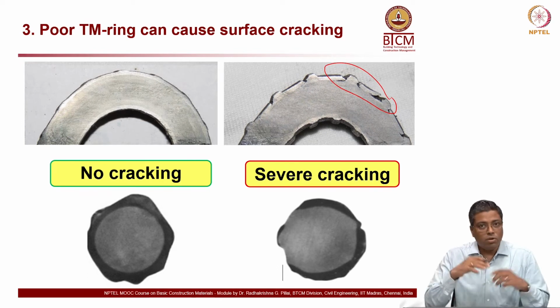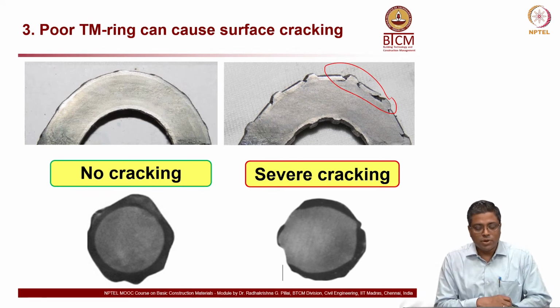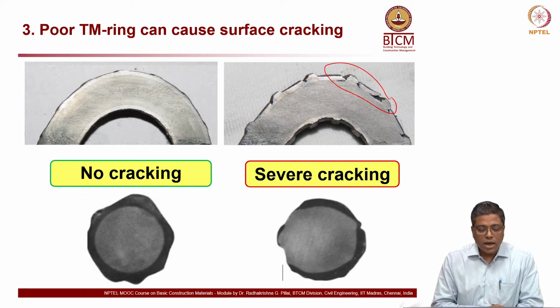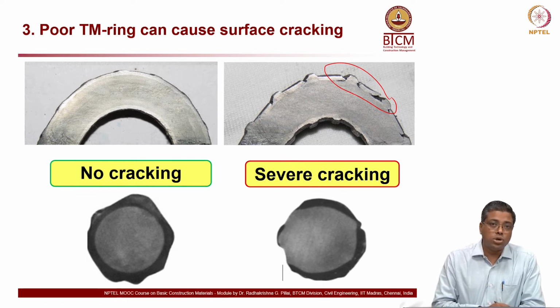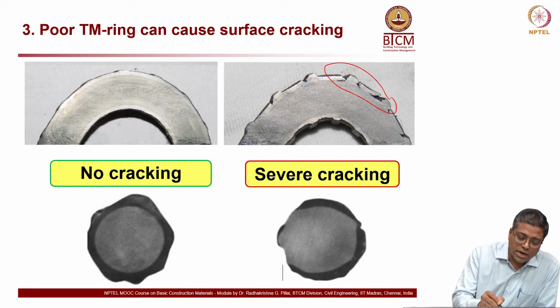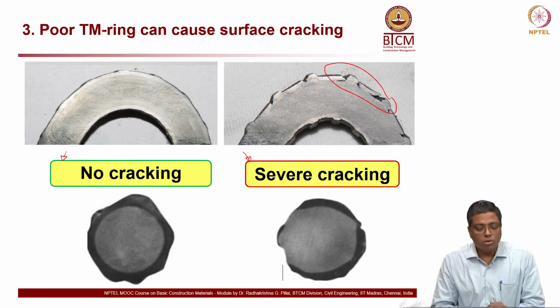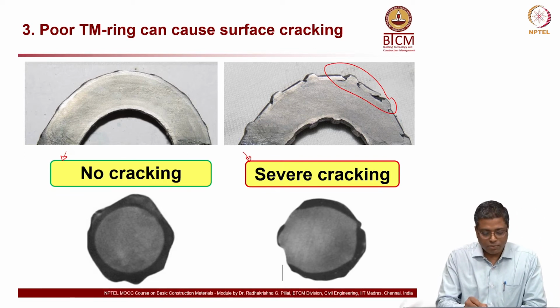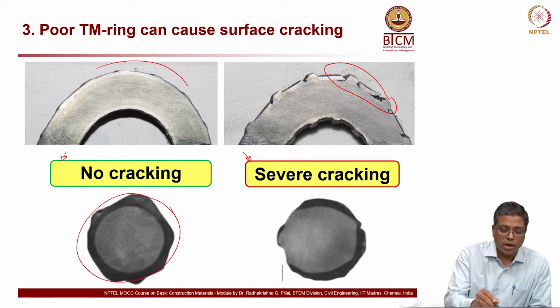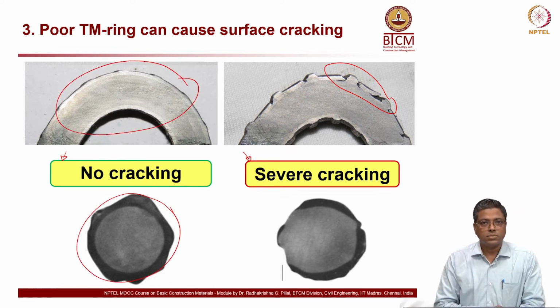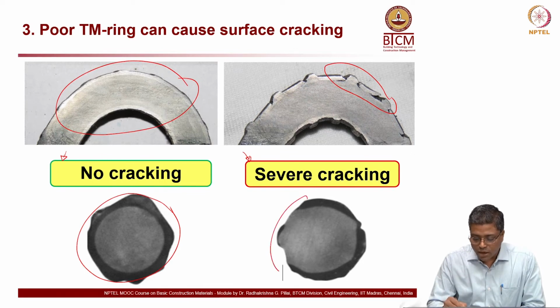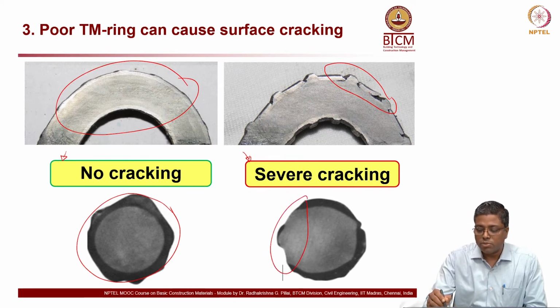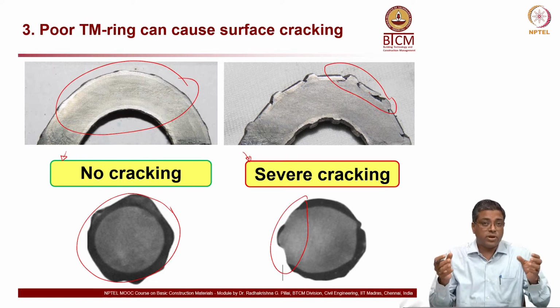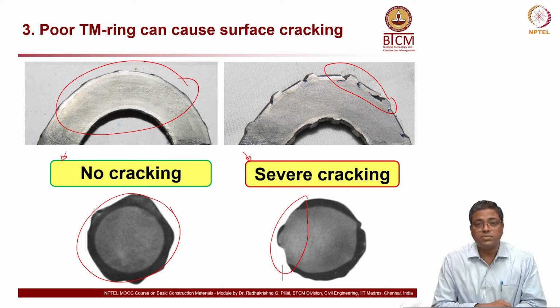And on the site, we always bend the rebars, right? We always have to bend the rebars. And when you bend the rebar, the cracking should not happen. So the picture on the left side is a good quality bar. I put this in green and the bad one in red, right? So a good quality bar, with a proper ring, even if you bend it, there will be no cracks. On the right side, a bad quality rebar, when you bend it, there will be a lot of peeling off of the peripheral region, which is very dangerous for the structure.